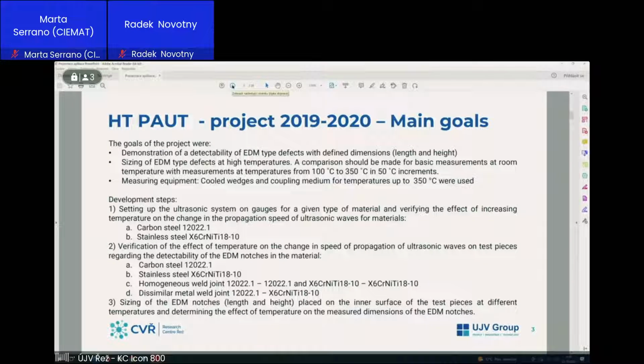The evaluation was done by comparison between room temperature measurements and measurements at temperatures from 100 to 350 degrees centigrade. What equipment were we using? We bought equipment from the Eclipse company from Canada. We have cooled wedges, and we are also using coupling medium for temperatures up to 350 degrees centigrade.